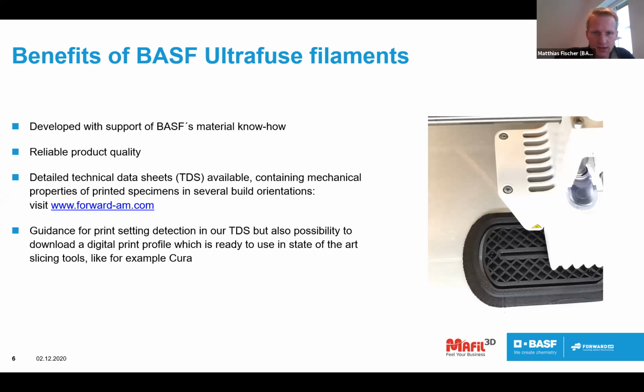And here we are really working hard to provide these also for our filaments, which means we are providing data sheets for filaments which are based on printed specimens to give our customers really a feeling how a material performs, not only in the best suitable build orientation, which is usually the flat one, where you can expect the best behavior in general, but also in other directions, like the upright build orientation, the Z direction, where you usually see the main disadvantages in filament printing.